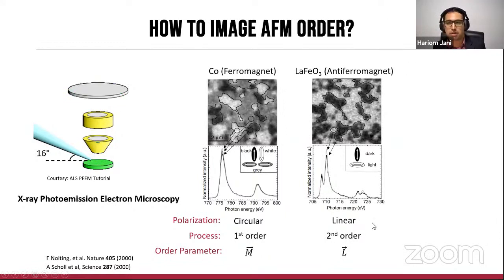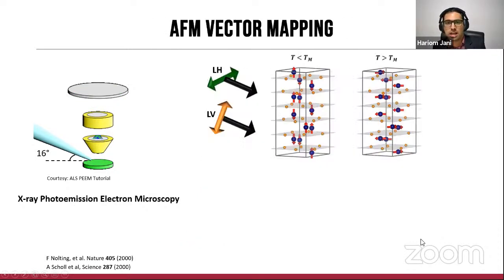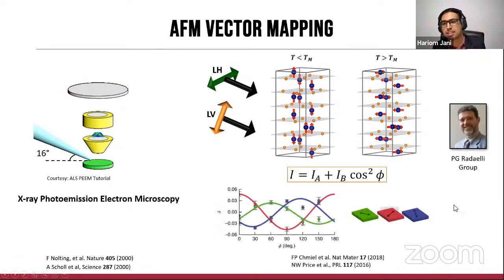But in this particular work, where they first showed the implementation of some of these ideas, very clearly there's a coupling between ferromagnet and antiferromagnet, and these techniques are very useful, resonant at the particular element edge. Now, in order to actually not only look at the overall structure, but to map the local variations, we do something called the AFM vector mapping. And this really is the brainchild of our very close collaborators at Oxford, Paolo Radaelli and his group, where they obtain this by using angle-dependent X-ray linear dichroism, and that is then integrated and fit to actually obtain various orientations of domains in the system.